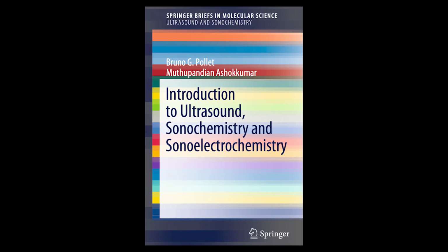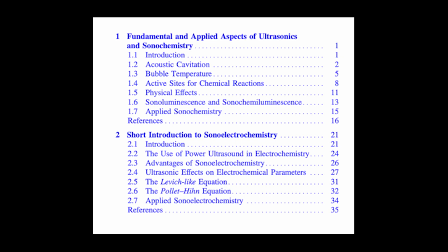And what's the range there? In MBSL systems, the experimental estimates usually fall somewhere between maybe 750 K and 6,000 K. Still incredibly hot, but a wider and generally lower range than the extreme SBSL numbers. Okay, 750 to 6,000 K, that's still a huge range. How did researchers try to get a more precise, quantitative measurement inside the bubble?